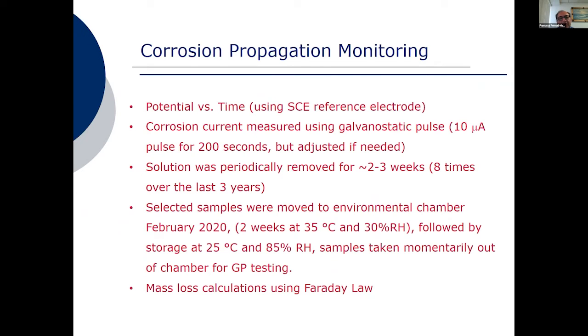During this part of the project, we monitored the potential versus time. Something I forgot to mention is that all these specimens were prepared in 2016. Then as part of the 3D LE project, we continued the monitoring, and we are reporting about 450 days of monitoring, but I'm including here the earlier data collected as well. The corrosion currents were measured using galvanostatic pulse, for the most part about 10 microamps and about 200 seconds. That allows us to obtain the potential of the rebar before starting the test, the solution resistance, as well as an approximate idea of the RC, and from there you can obtain the corrosion current. Since we don't know the area of the rebar that is corroding, we kept these values in corrosion current rather than corrosion current densities.